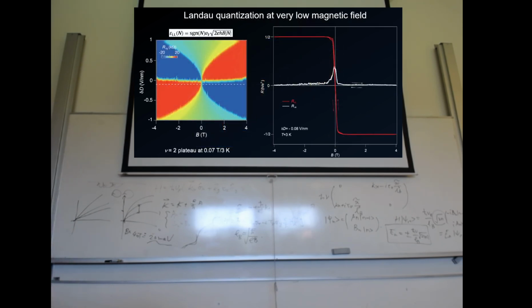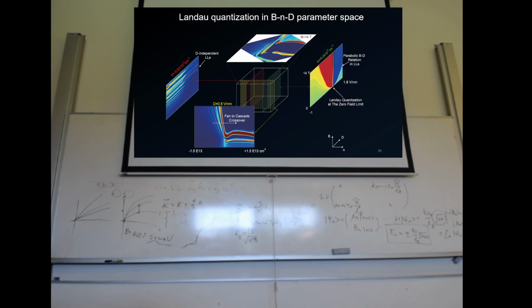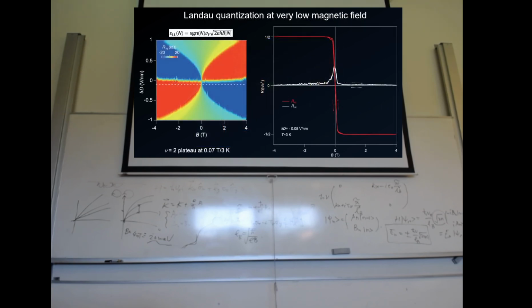If we look at a line cut of this mapping again, which is the one I showed you on the right hand, and you make a line cut close to delta D equal to 0, which is this line, you will have a quantized plateau showing up, which very likely mimics quantum anomalous Hall behavior. Instead, quantum anomalous Hall has a residual quantization even when B is equal to 0. Now we need some finite magnetic field to see this phenomenon.